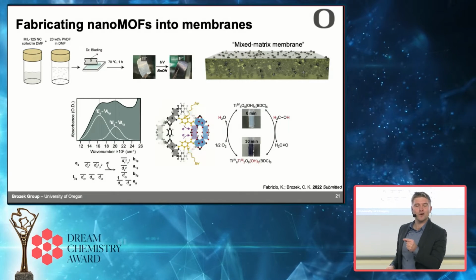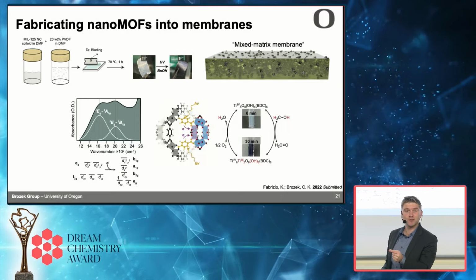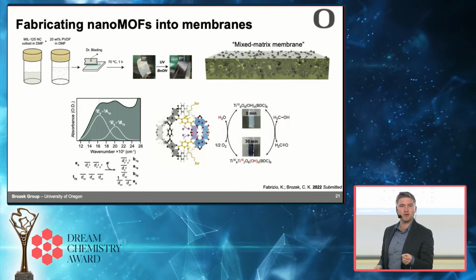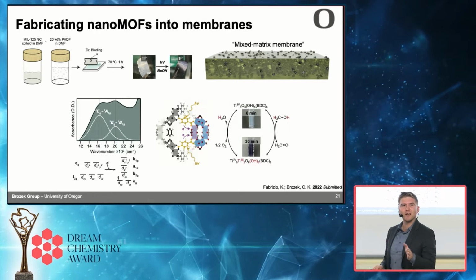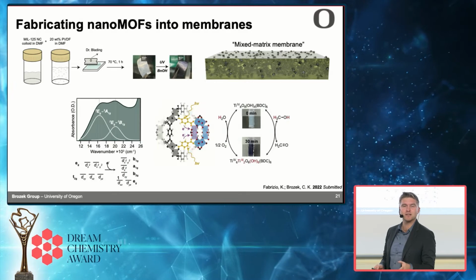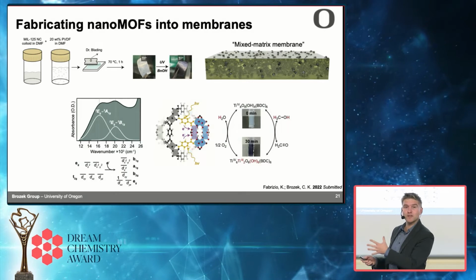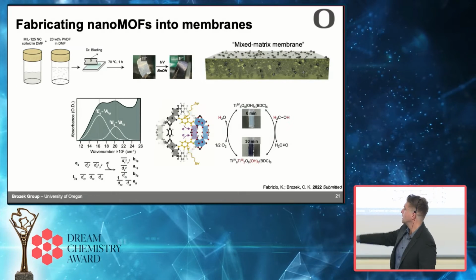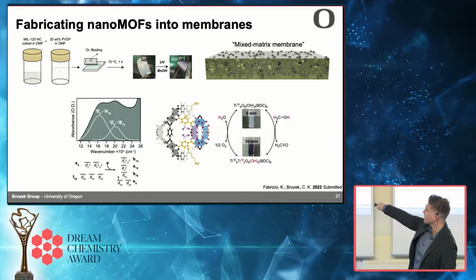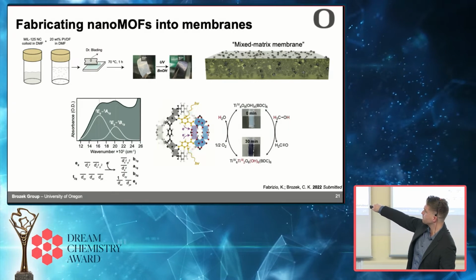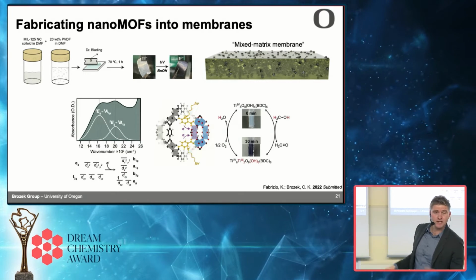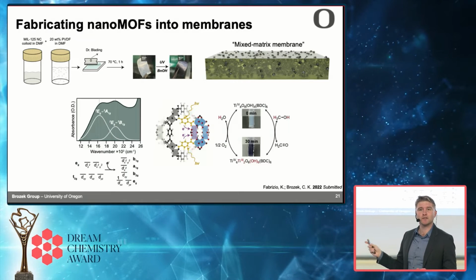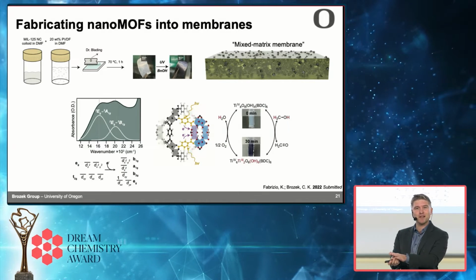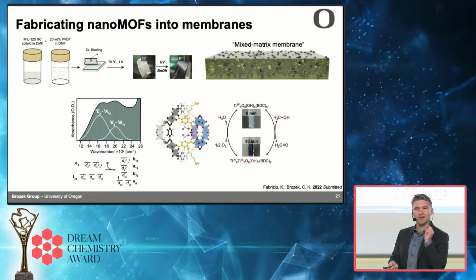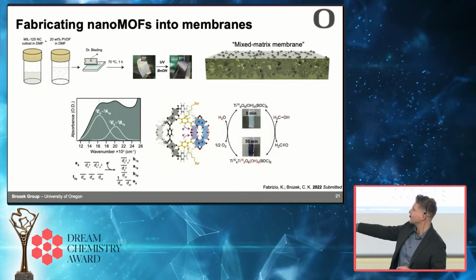But we can also use these as a solution and use solution state UV-vis spectroscopy. So basically up to this point, if you were to characterize a MOF, you had to use solid state techniques. But now we can treat them almost like solutions. And so here's a solution state UV-vis spectrum of the particles. And these are the d-to-d transitions, hallmark d-to-d transitions for titanium 3+. If you open up a standard undergraduate inorganic textbook to octahedral titanium 3+, this is what you see.